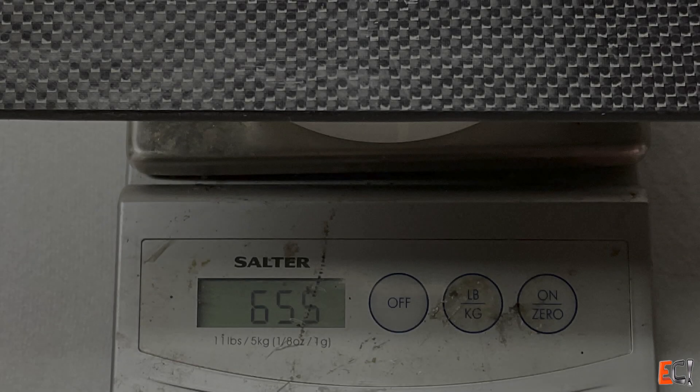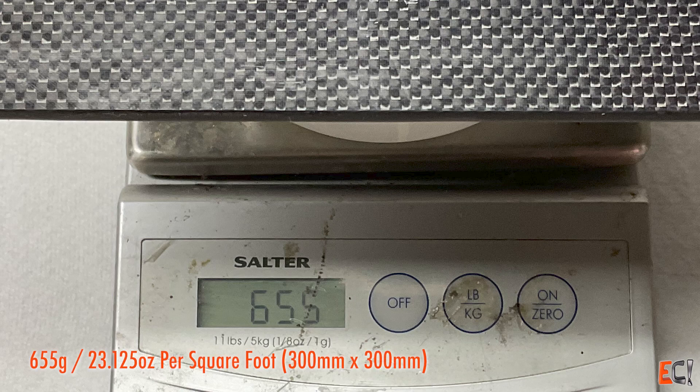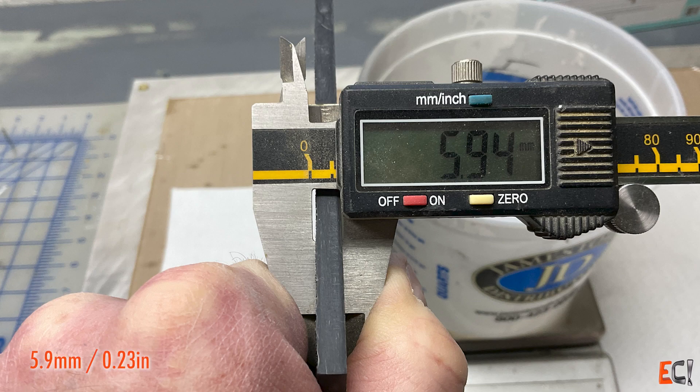Here's through a microscope. I tried to get it, but it's hard to see. You do get a sense that it's really a uniform all-directions material. The weight was about 655 grams, 23 ⅛ ounces for that one square foot, and just under six millimeters or about a little less than a quarter inch.